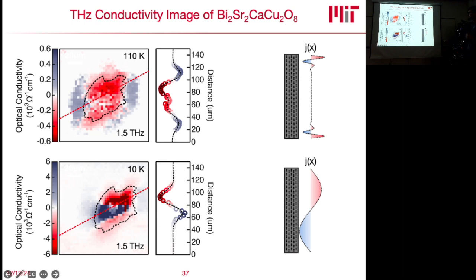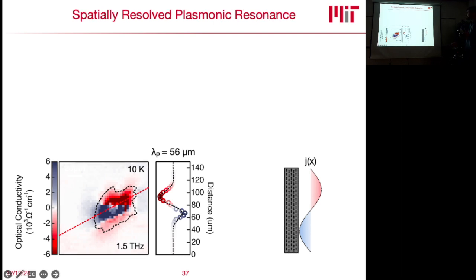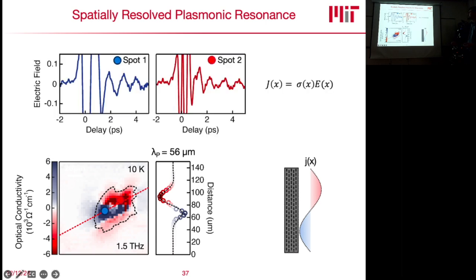If you take a line cut along the diagonal, you get something that only shows something at the edges, as we would expect. Also note that this is a very, very different color scale. And here you get this very nice sinusoidal pattern. If you compare it to this example here, it makes sense. This is a plasmonic resonance. And now we can, of course, take its wavelength and take its momentum.